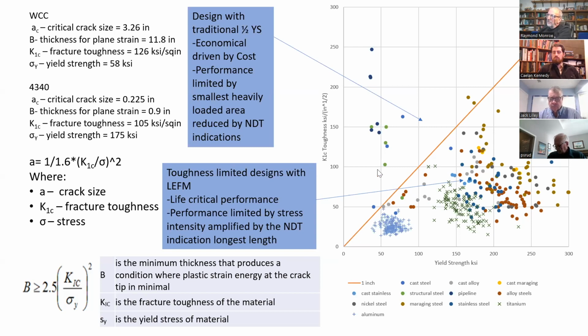So he tells that the carbon steel materials are here, the alloy steel materials are here, and when I really want high strength material, the Mar-aging steels or the things you used to make, Paul, for ground engaging tools, I'm way out here where I have 50 KSI sort of as a minimum fracture toughness, and I may have a yield strength that's 150 or 200. And if I'm up in the 200 range, then I've got less than a ¼ inch critical flaw size. But what this really means is that for most of our materials, they're really not fracture sensitive. They're really primarily plastically driven.